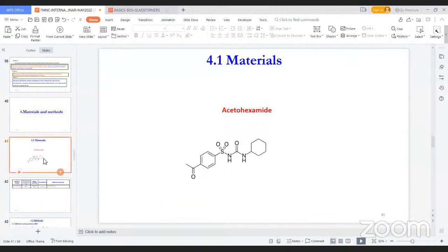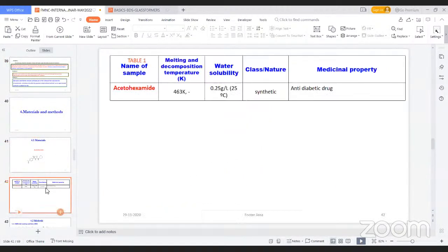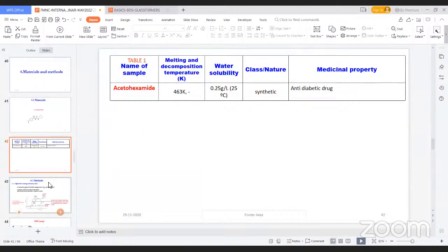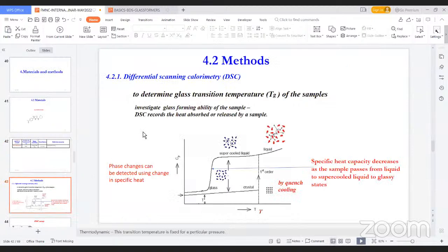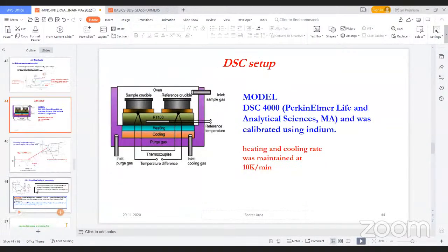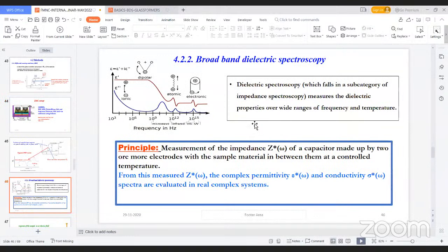So the material which I took is acetohexamide, an anti-diabetic drug, and its melting temperature, water solubility, all these things are noted. And DSC is used to understand the glass transition temperature, and the dielectric spectroscopy is used to understand the molecular mobility. This is the principle of the measurement. And here you can see the frequency range, 10 raised to -2 to 10 raised to 9 hertz, where the dipolar relaxation, that is orientational polarization, is the reason that causes a change in the dielectric constant or the dielectric spectrum.